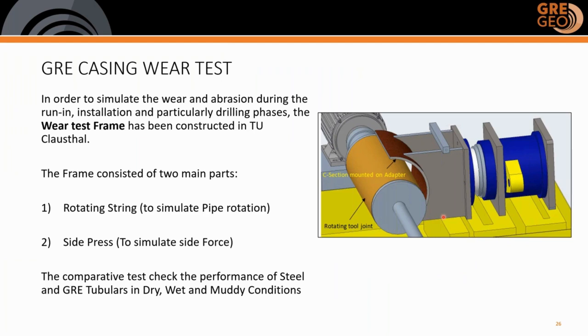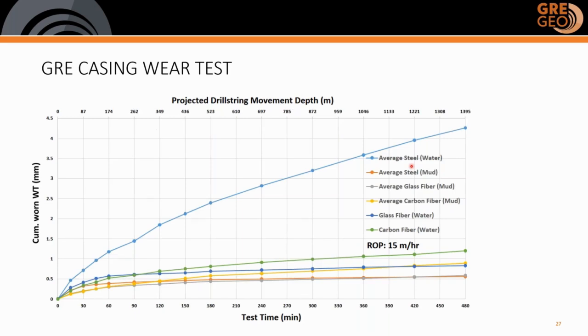So the wear: one of the questions that always rises in this kind of subject is whether the GRE liner or even a pipe can withstand the wear, since it's not made out of steel. So we made a rotary tool setup in order to test the capabilities of the pipe. In this darker red, you may see the piece of the pipe, whereas the rotating tool joint will be simulating, so to say, the internal drill string. We can also change these, and then we would be able to simulate the wear of the casing against the well walls.